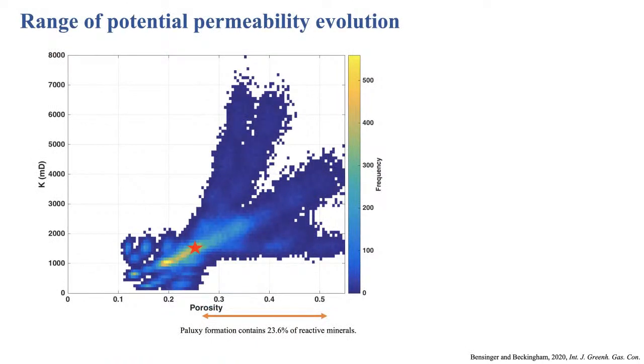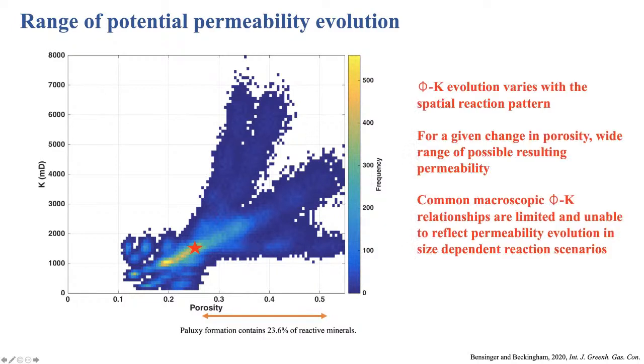And so if we think about what's going to happen at the Paluxy formation once we inject CO2, this particular sample or formation has about 24% reactive minerals. So the star is the initial porosity and permeability. And so if we think some of those things are going to dissolve, we could have a large range of potential porosity permeability evolution.